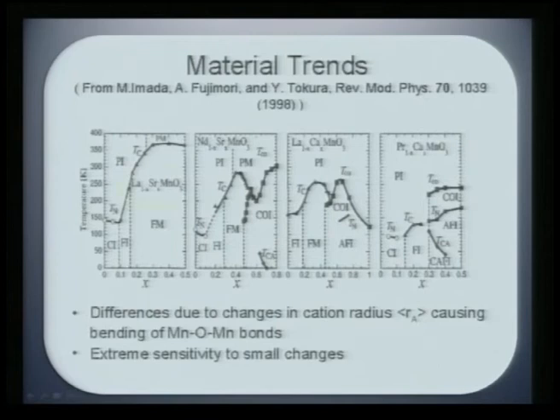LaSr MnO3, you can see up to 0.5 you can have TC, and then it slowly transforms to a charge ordered state. Neodymium strontium manganate, here I am changing the lanthanum by neodymium, again you would see after a ferromagnetic state around 0.5 a charge ordered insulating phase coming. Similarly, the case for praseodymium, it is more complex than other series, because praseodymium itself has a variable valency, as a result the MIT and ferromagnetic transition gets distorted.